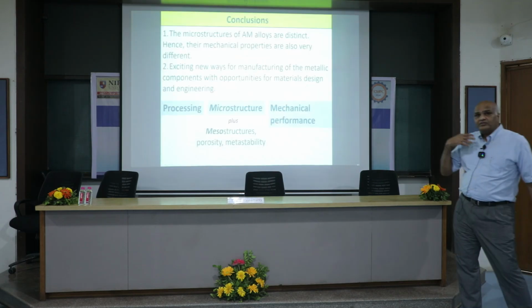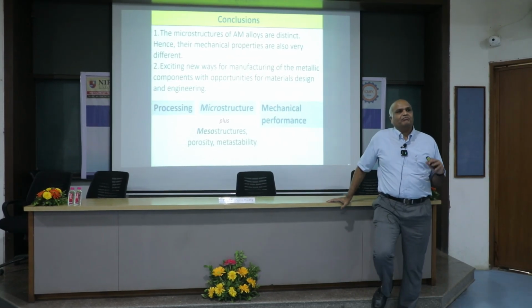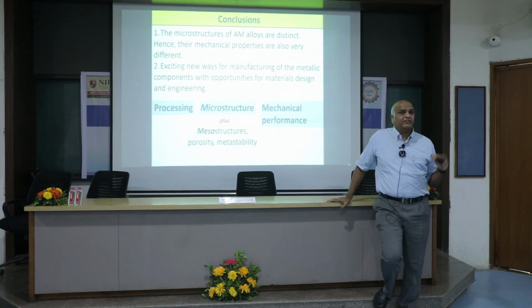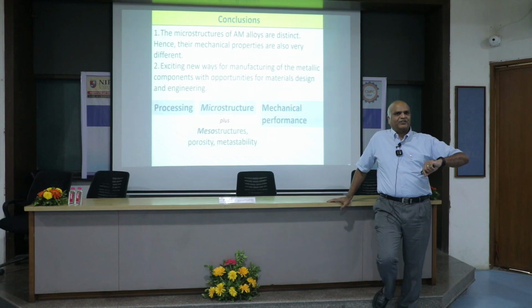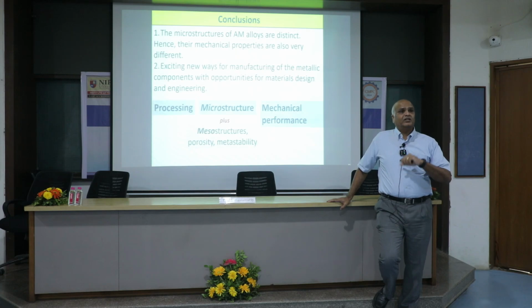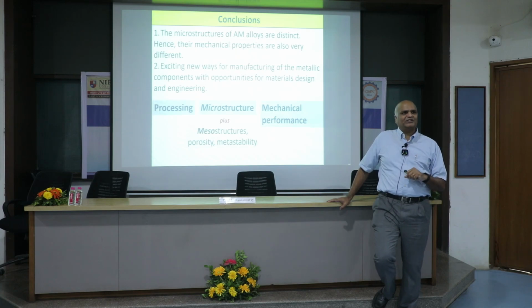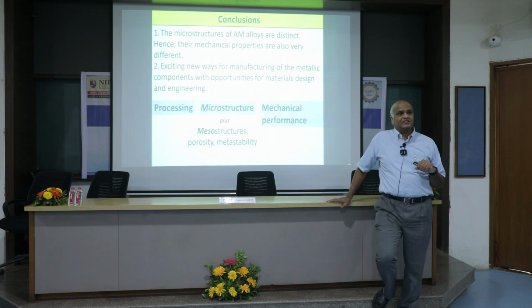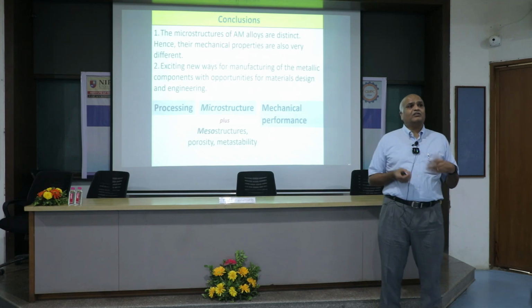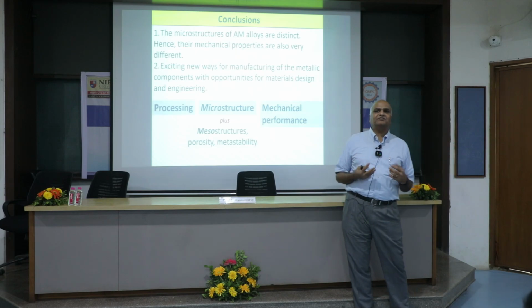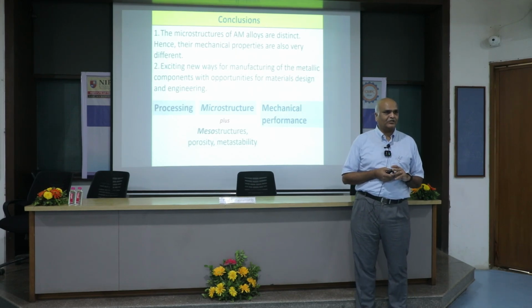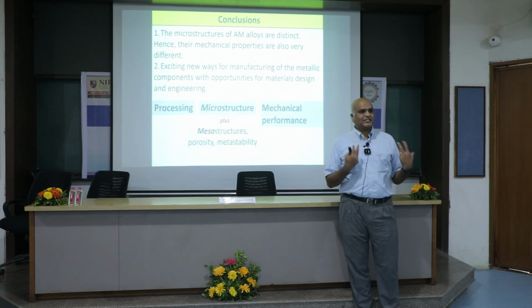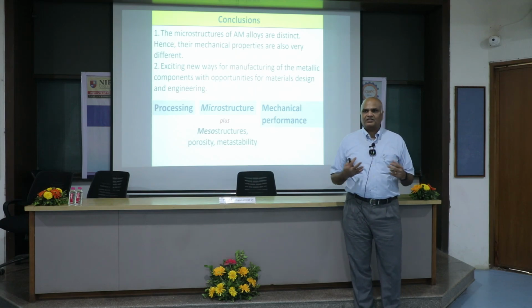All right. So hopefully I convinced you that the microstructures of the 3D printed alloys are very distinct, very different from conventionally manufactured alloys. Same alloy, if it is conventionally manufactured, you get one microstructure; 3D printed, a different microstructure. As a result, they change the mechanical behavior, and you need to understand those before you can really comfortably use them in applications where structural integrity is very critical. But it also gives you new exciting ways to tailor microstructures and manufacture components. So a lot of times people now talk about bespoke microstructures for given applications.